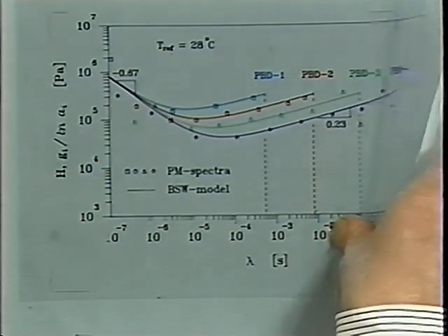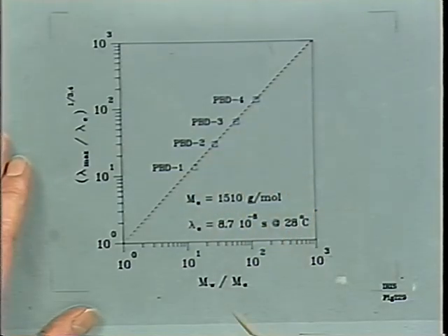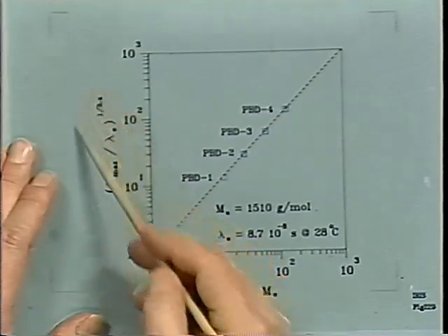You can see how powerful it is, how nicely it helps us calculate things. The cutoff relaxation times, again, follow a slope of about 3.4. These are for the 4 samples, and the 3.4 power is put into the axis here on the side. So no surprises. It's really the same behavior for the polybutadienes as for the polystyrenes.